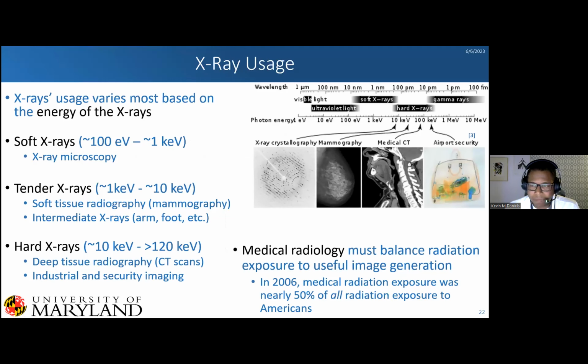And so what sent us down this path was talking with the School of Dentistry at Maryland, and they were interested in generating X-rays to try to do X-rays for teeth without completely flooding them out with X-rays. And for instance, if someone has a filling and you try to do an X-ray near that filling, it's very, very difficult. Those regions will actually light up and block any kind of vision you have on, let's say you have a cavity nearby.